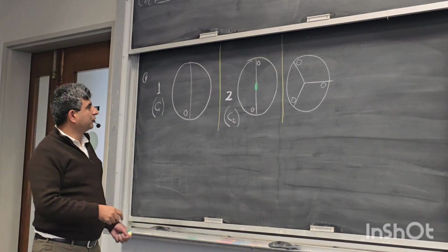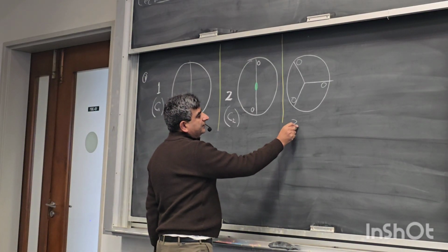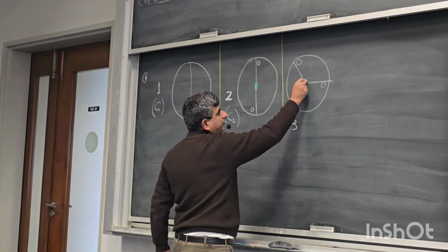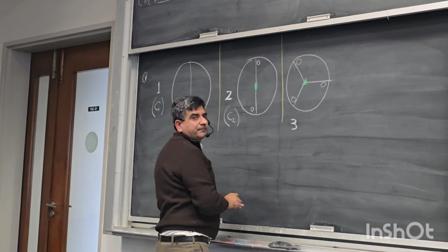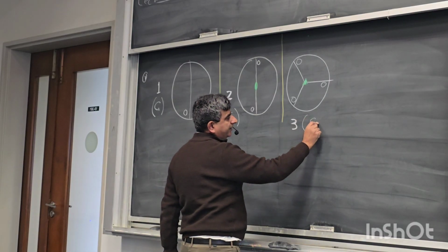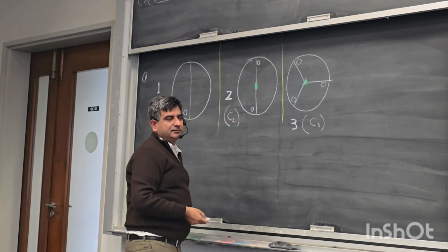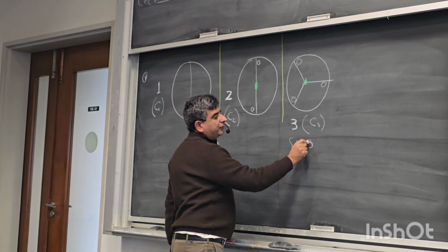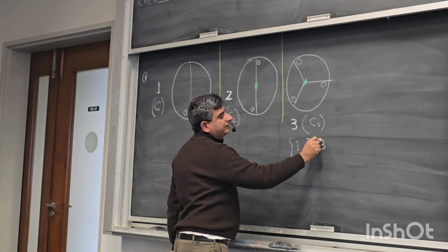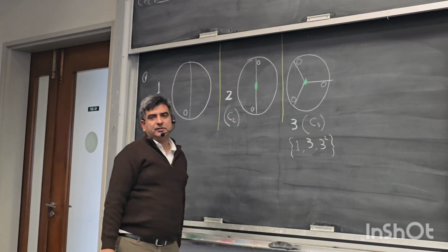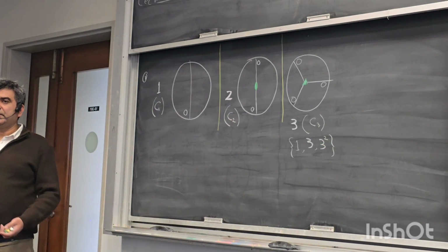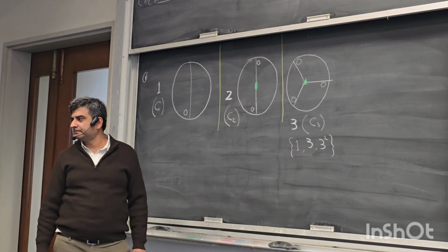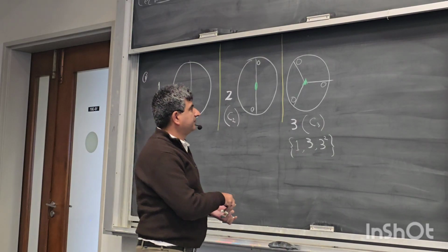Okay, so this group is given the symbol 3 because really there is a threefold axis of rotation here. In the old notation, this is called C3, and it has 3 elements. The elements in this group are 1, threefold rotation, and threefold rotation done twice, right? So it's a threefold group, but the point group itself is labeled as 3. Okay, so let's do the next one.